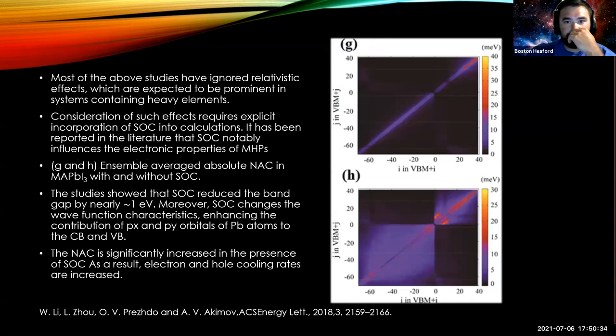And so lastly, most of the above studies have ignored relativistic effects, which are expected to be pretty prominent in systems that contain heavy elements like lead. Consideration of these effects requires explicit incorporation of spin orbit coupling into calculations. It has been reported that spin orbit coupling influences the electronic properties of the perovskites.